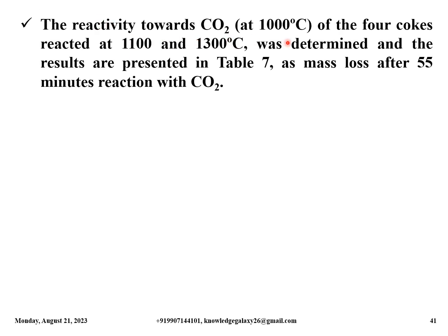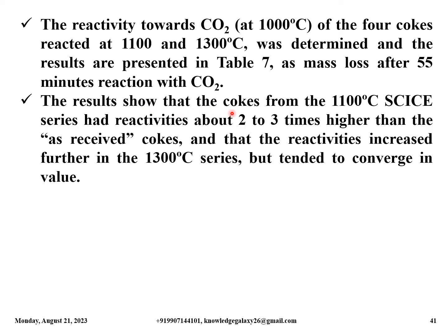Okay, let's move on. The reactivity towards CO2 at 1000 degrees Celsius of the 4 cokes reacted at 1100 degrees Celsius and 1300 degrees Celsius was determined, and the results are presented in table 7 in the coming slide as mass loss after 55 minutes reaction with CO2. The results show that the cokes from the 1100 degrees Celsius SCICE series had reactivities about 2 to 3 times higher than the as-received cokes, and that the reactivities increased further in the 1300 degrees Celsius series but tended to converge in value.